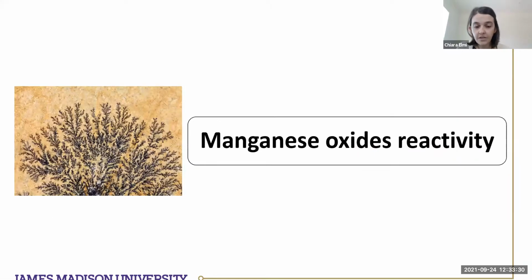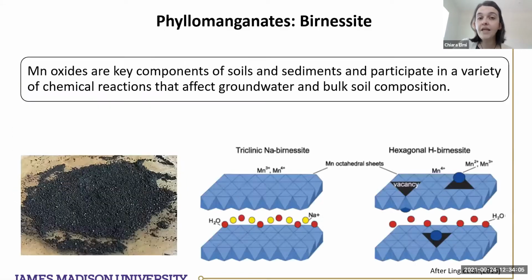Okay, so based on these studies related to the reactivity and crystal chemistry of micas, another project I focused on was the manganese oxides reactivity. Manganese oxides are very common, in particular in Virginia. It's possible to notice these dendrites in sandstone and sometimes in limestone too. They are black in color, and they are super common in soil like micas. They are called phyllomanganates because they form layers. So in this case it's not a TOT, but just one layer of octahedra with manganese 3+ and 4+ in this layer.